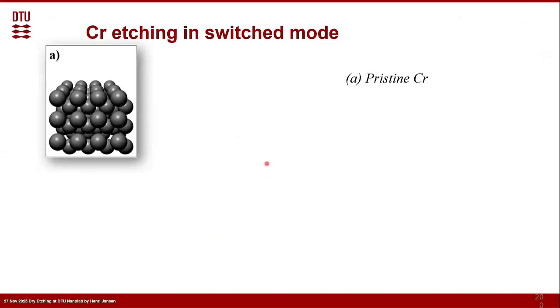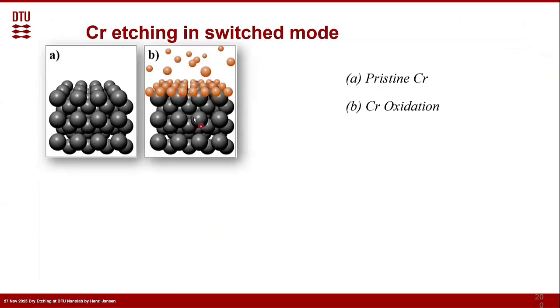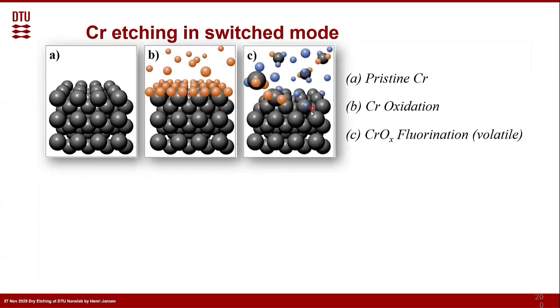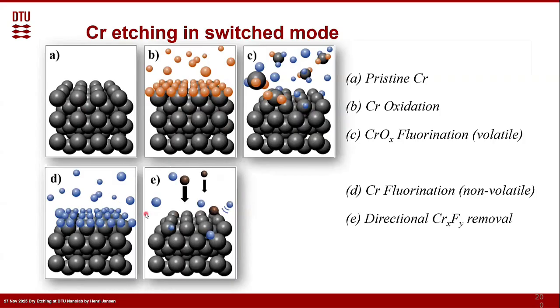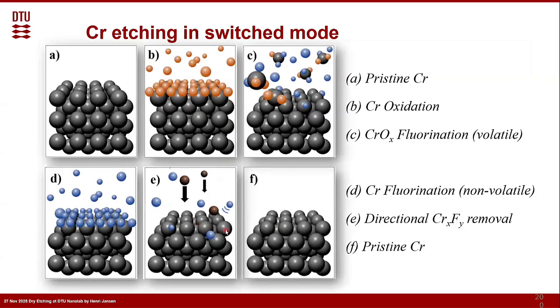But what happens now for chromium etching is that, if we start with pristine chromium, the first thing that could happen is you oxidize it in the cryo process and you create chromium oxide. But the chromium oxide can be directly etched by fluorine. Not the chromium, but the chromium oxide can be etched, and it is removed. But then after a while, it will be fluorinated. But this one can be knocked away very easily, the fluorine radicals, by ion bombardment. And then again, you are back to the chromium layer, which can start again to be oxidized, and you go in a cycle. You can call it a type of atomic layer etching. Good.